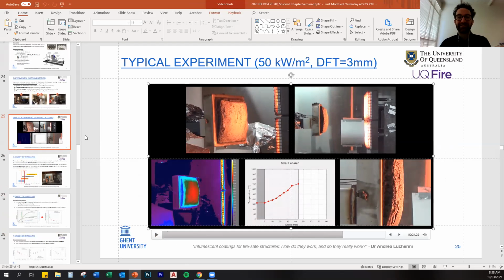Thank you very much for the question. Very good one. First, the concept about the swelling. The radiant panels have a certain size, as I mentioned, 300 by 400, and my samples were 200 by 200. These sizes were decided in order to get a homogeneous distribution of incident flux at the coating surface. But then, as you correctly highlighted, you can see some sort of different swelling, or edge effects, at the coating edges.